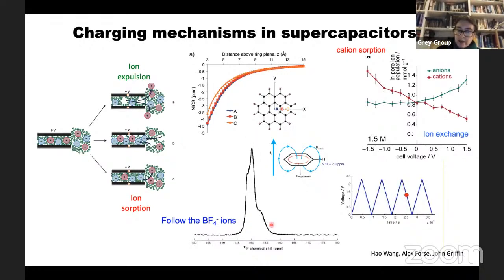So the shift to the right is a ring current, and is exactly the same thing that you see when you do NMR spectroscopy of benzene. In benzene, you have a very large shift of about plus 7.3 ppm, and that's due to the ring currents in these benzene molecules. And because the protons are here, you get a positive shift. And so those of you who are following, this is actually a negative shift. The reason it's negative is that the ions are sitting on top of the graphene sheets. So they're not single rings, they're really more graphenic sheets, and they're more like these sort of coronenes or dicircumcoronenes. And so this is showing you a DFT calculation, which is predicting that if you're sitting on top, then you get a negative shift.